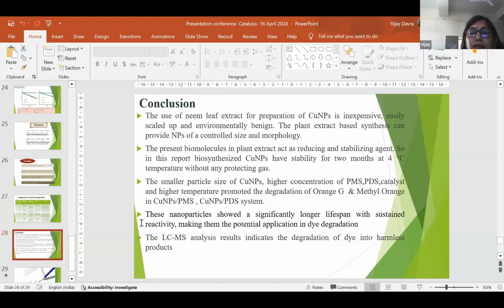And the conclusion of the total study is that the use of neem leaf extract for the preparation of copper nanoparticles is inexpensive and an eco-friendly route, and plant extract based synthesis can provide nanoparticles of controlled size and morphology. The phytochemicals present in the plant extract act as reducing as well as stabilizing agents, so we can prepare the nanoparticles without any protecting gas.